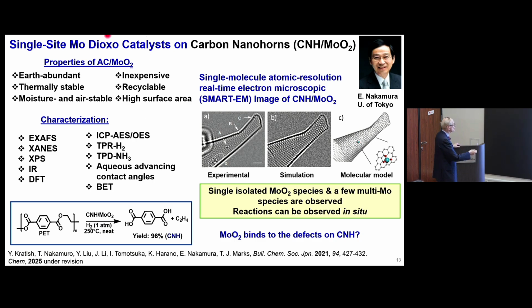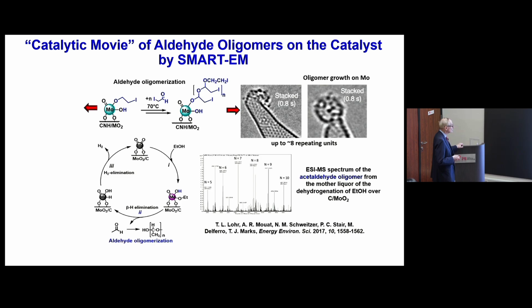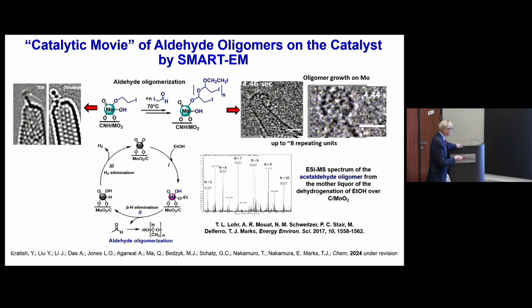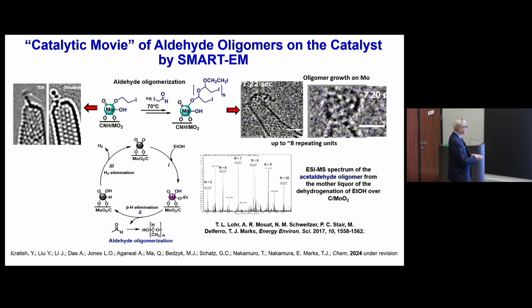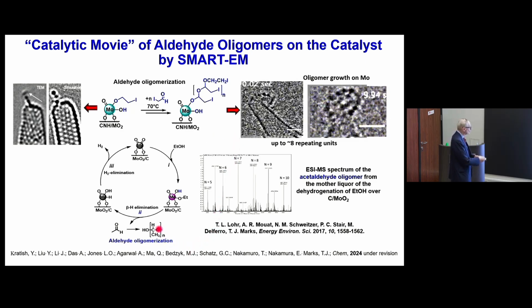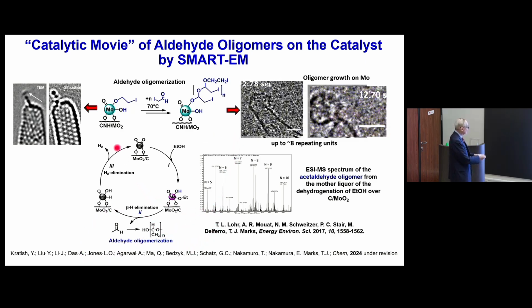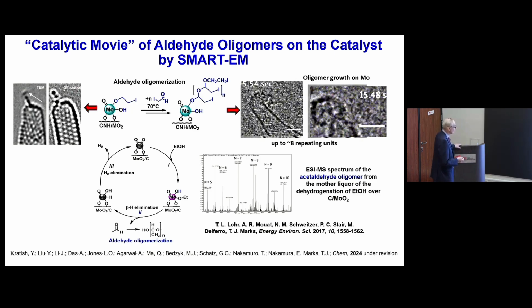And we do all of these control experiments to make sure that the catalyst on the carbon nanohorn is the same as the catalyst on our other carbon supports. And here you can see the carbon molecules here, the molybdenum molecules here. And now let's use it on a real reaction. And the real reaction we're going to use is one that Tracy Lohr discovered. I mentioned it already, and this is to take ethanol and do this cycle to kick off an aldehyde and hydrogen. And it's very fast.